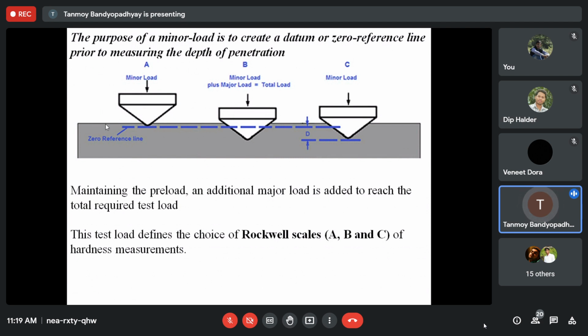So for that, initially we apply a minor load of, say, 10 kg force on the specimen so that it indents a certain height. This height is not written here; we call it the indentation depth, say delta. After I indent by a depth of delta, I have to keep the load there for a certain amount of time. Why? Because this delta has two parts, an elastic part and a plastic part. So I have to allow a certain dwell time so that the elastic part recovers by itself and only the plastic part remains. Whatever plastic part remains, that depth forms the zero reference line from which I can continue the depth measurements on the surface.